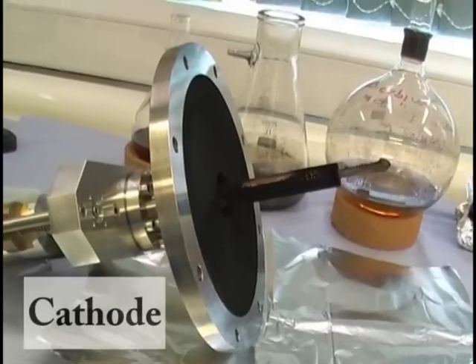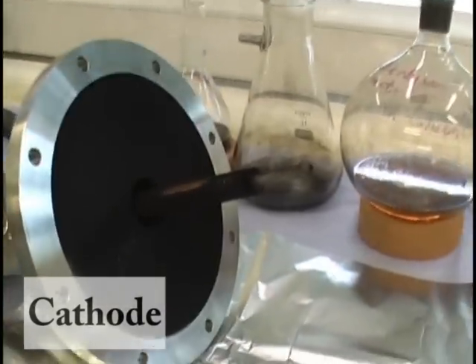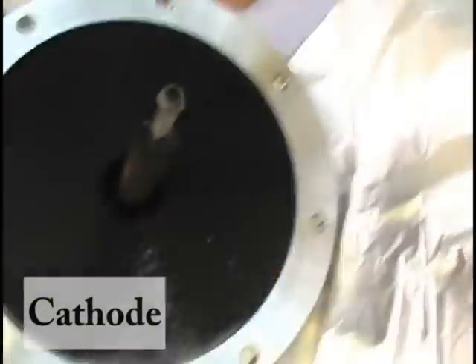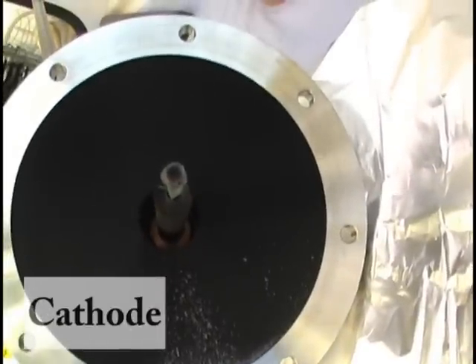On the cathode there is also black powder, where we will find carbon nanotubes, normally with 20-30 walls, although if we also include a metal catalyst in the anode we can obtain single-walled nanotubes.